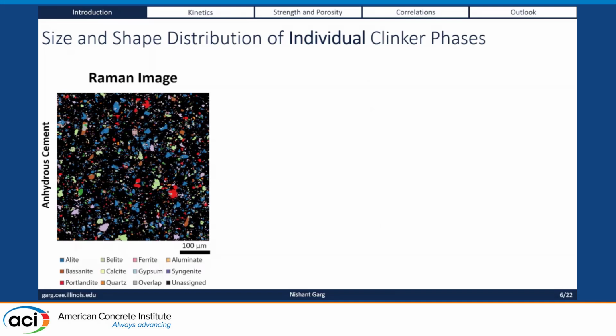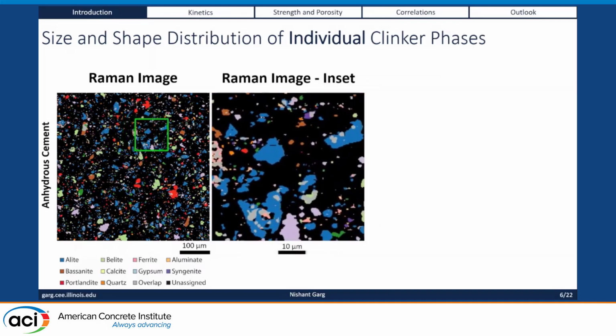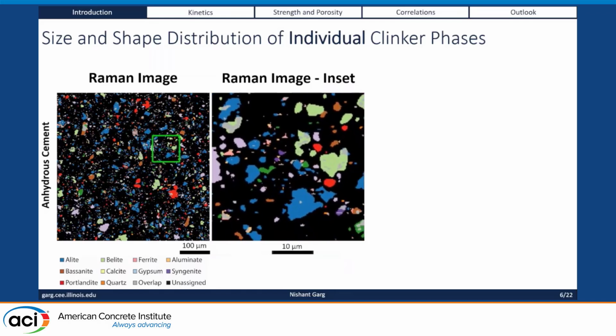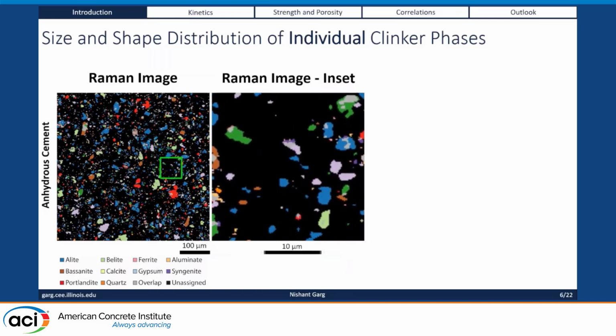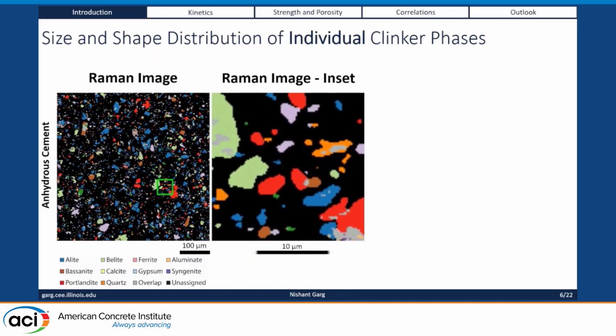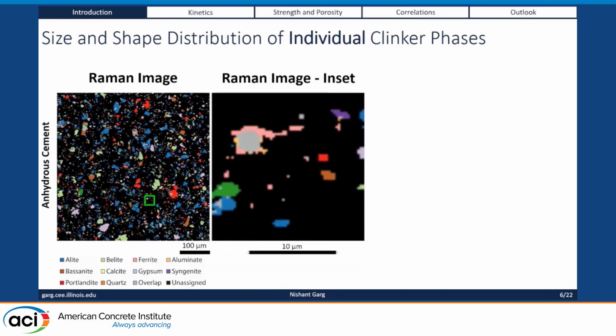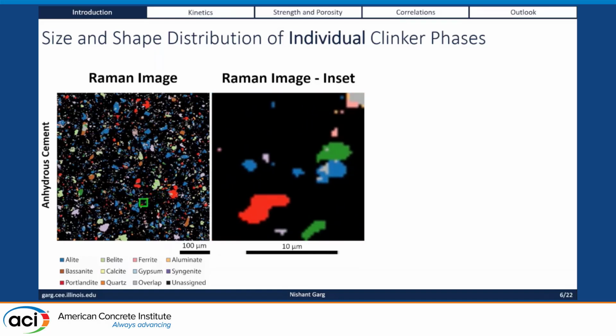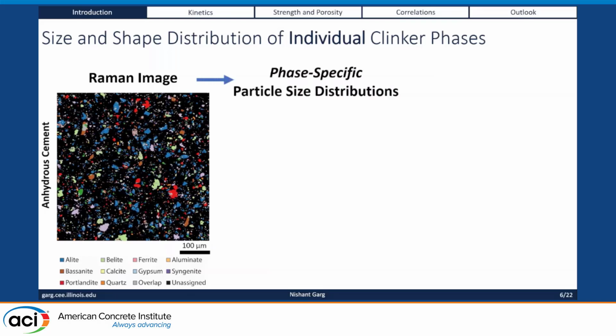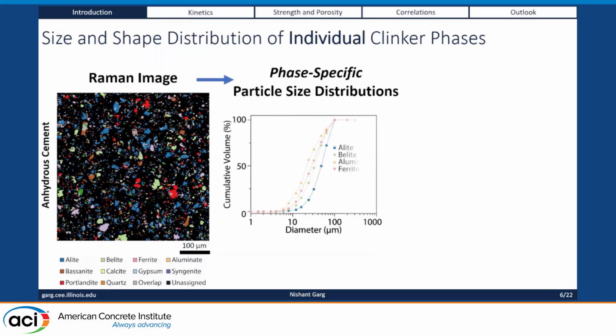So what else can we get out of this? Well, you can actually get the size and the shape distribution now of individual clinker phases, right? Again, this is just a short animation of going through the different phases that are distributed in this image. And then you can quantify this through image analysis, and you can get what we call the phase-specific particle size distributions, right? So instead of having a global PSD, you can get the PSD for each component within the cement. So all the way from alite down to calcite or quartz.